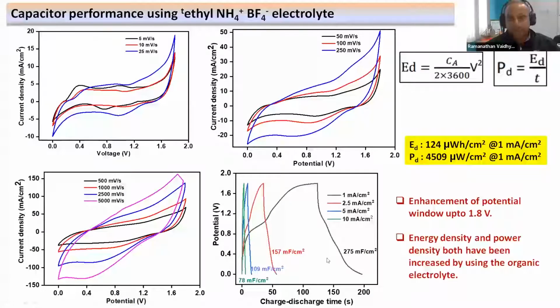And what did we get? Yes, we could see that we could expand the potential window beyond 0.8 volts, and we could go all the way up to 2 volts. And naturally, we have expanded this potential window. And we also got excellent specific capacity for this material. Put together in the charge storage, you're able to see 275 millifarads per centimeter squared of capacitance coming from an all solid state material. This is not a gel electrolyte. This is a solid state electrolyte.